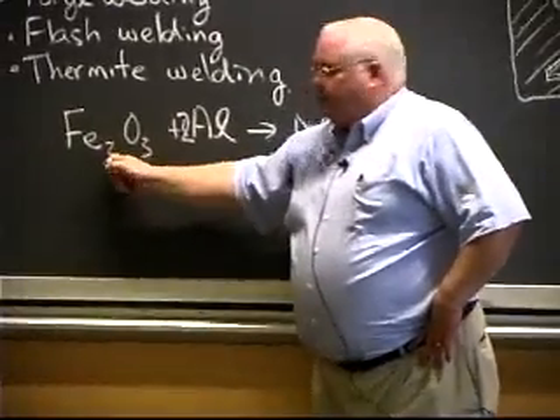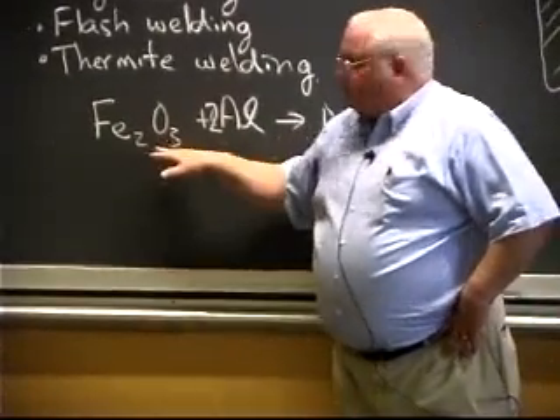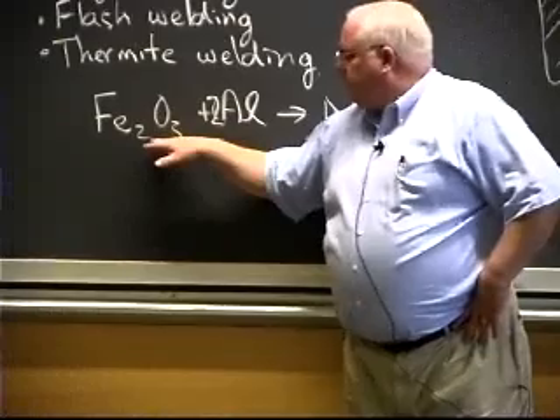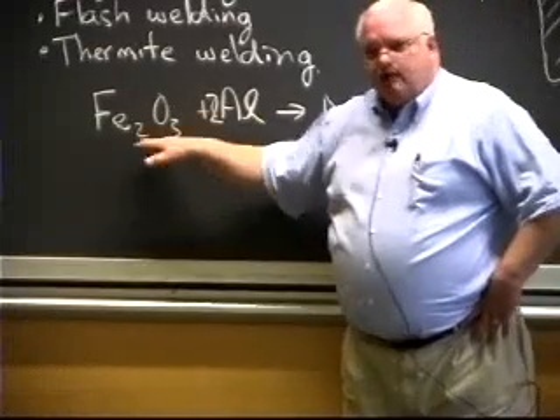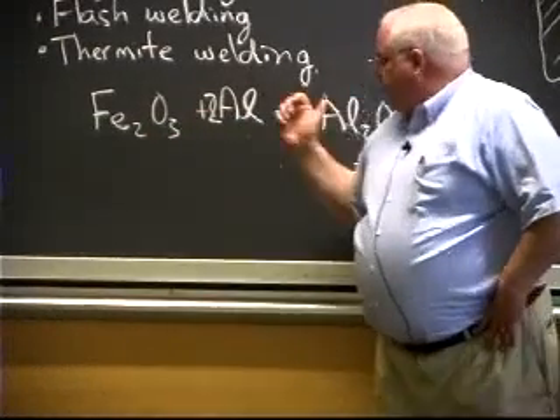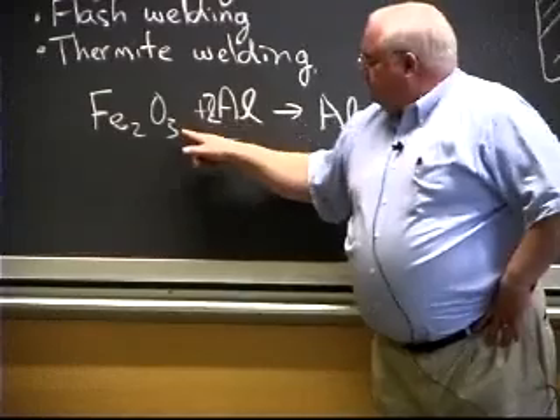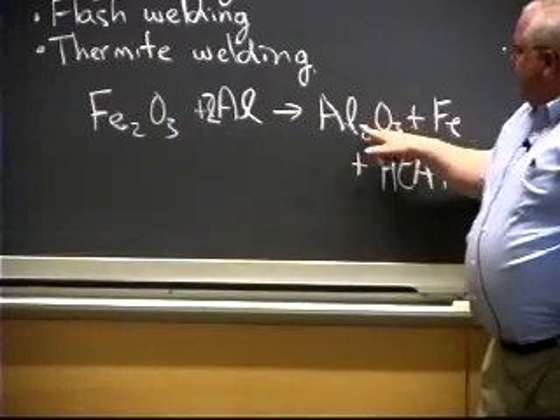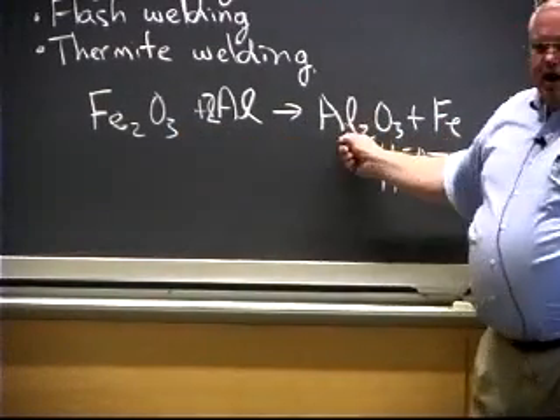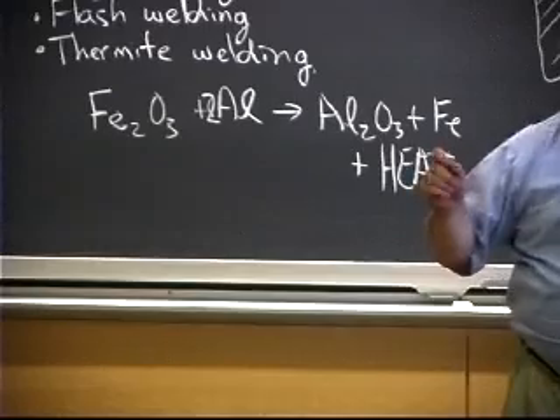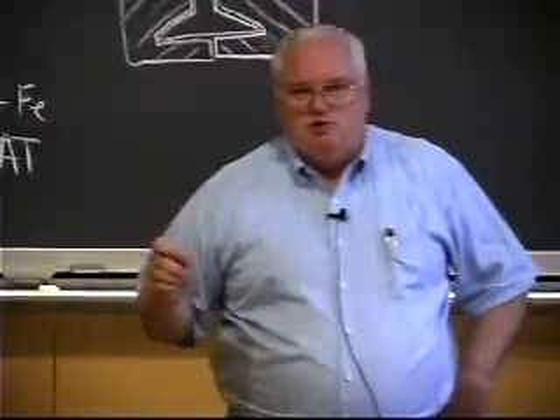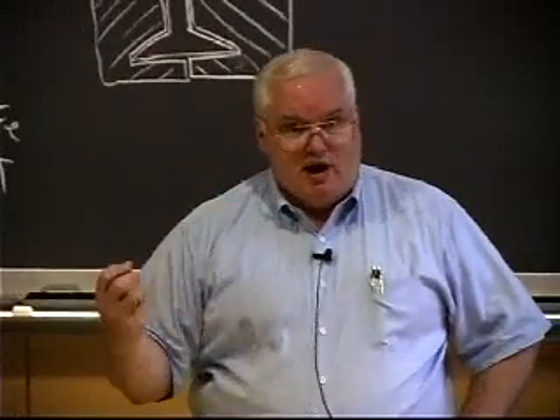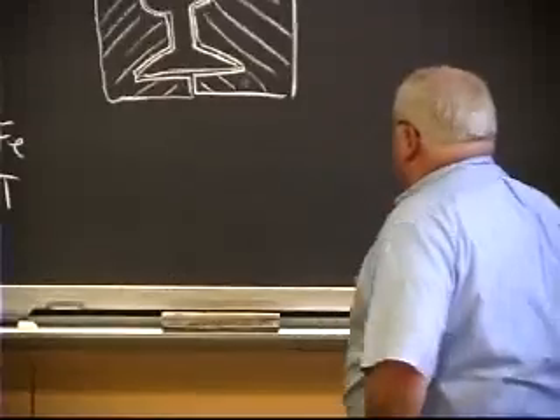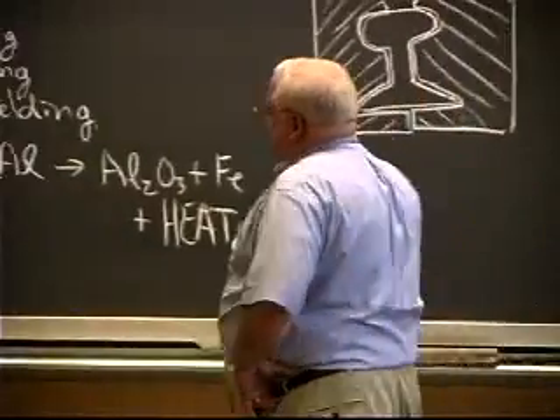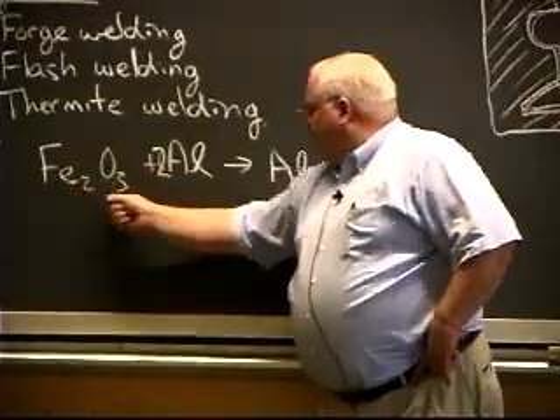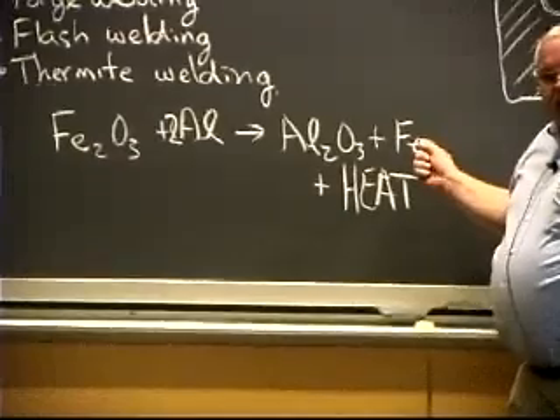The iron oxide is probably Fe3O4, magnetite. This is rust, hematite. There's also wustite, which is FeO, but who cares? This one was easier to balance. Fe2O3 plus 2Al goes to Al2O3 plus iron. Aluminum oxide is much more stable than iron oxide, about 3 times in terms of the energy of reaction thermodynamically. And so basically the aluminum reduces the iron oxide to form aluminum oxide and iron.